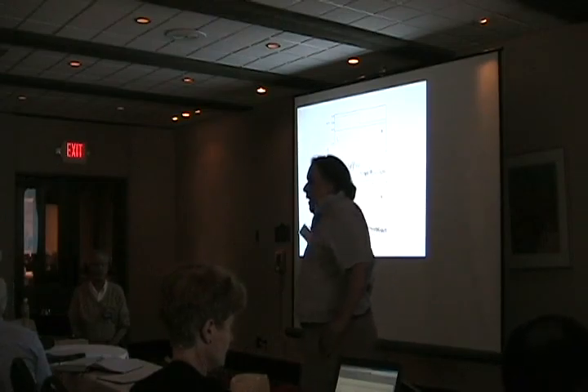Well, absolutely. And that's why we don't use the molecules on metal. We're always using indium tin oxide. It's conducting, but not really a metal. But even though we're using indium tin oxide, which is a semiconductor, John will be talking about it, it still has 50% quenching. You mentioned gold. Gold may be very strong. Right. So with gold, we tried to deal with this and push the molecules off the surface of the gold.